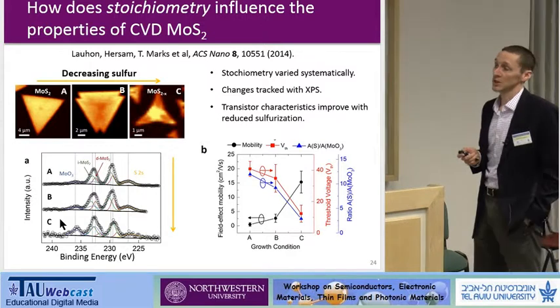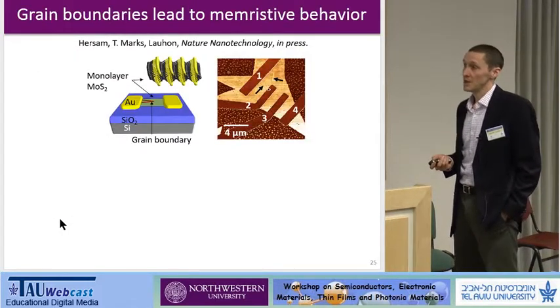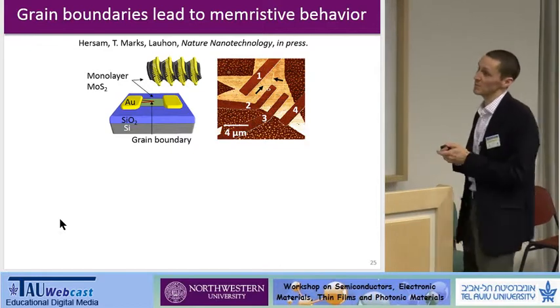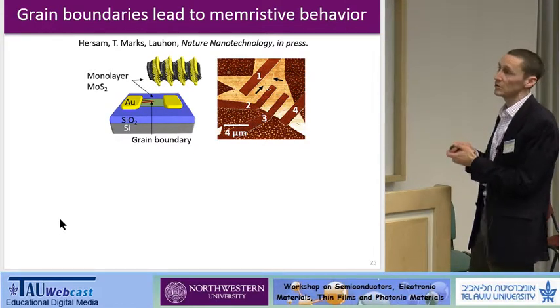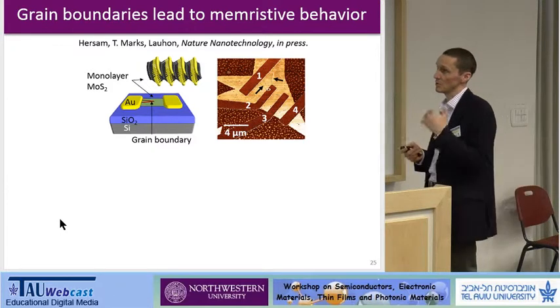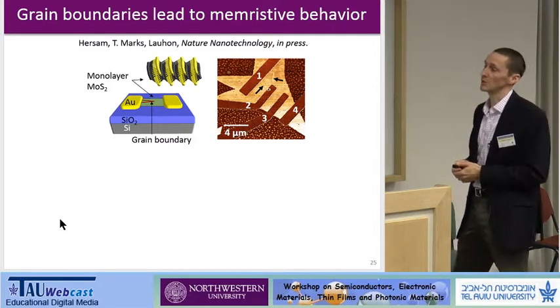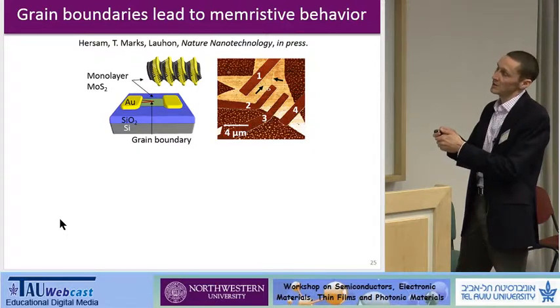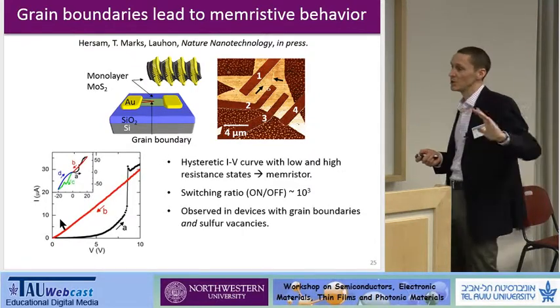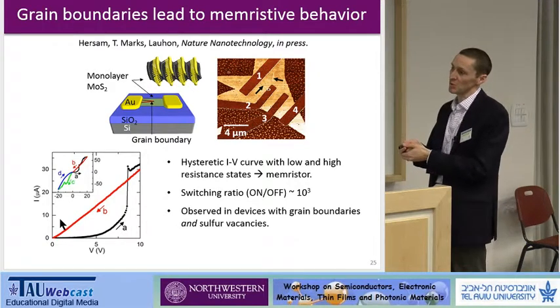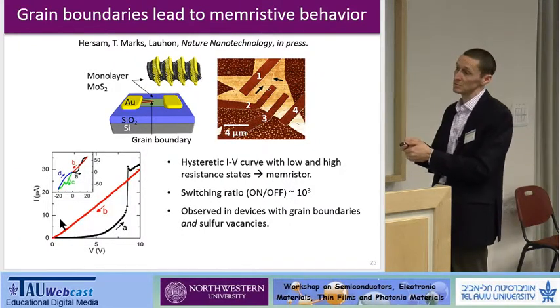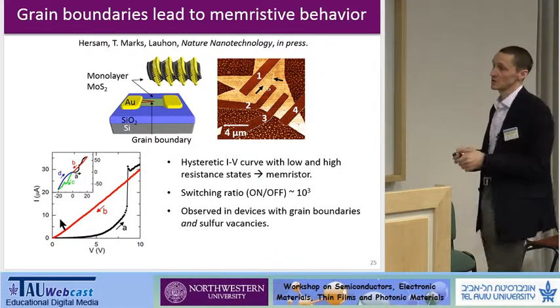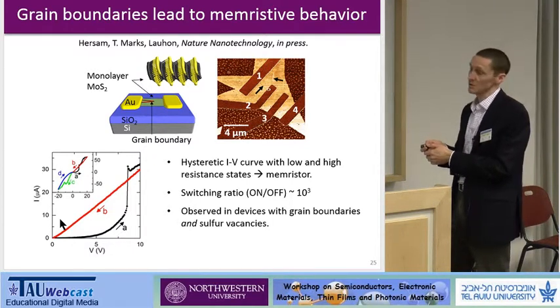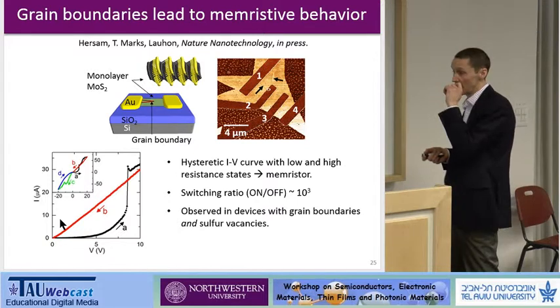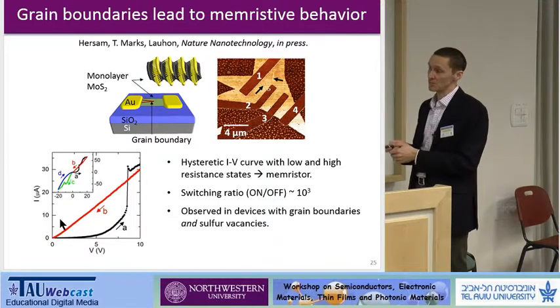But what's more interesting about these particular defective materials is that when they're sulfur deficient and they have grain boundaries at a particular geometry in the channel, they show memristive behavior. I think Mark will probably talk a little bit about this as well, and I won't go into it in detail. But in devices where there's a grain boundary within the channel, you can manipulate that grain boundary and see essentially a memory effect. There's a certain bias at which the device turns on to a higher conductance, and it will stay there upon decreasing the voltage. Okay, so this is the foundation for what is called memristive behavior with reasonable on-off ratios. And it occurs in devices, as I mentioned, with grain boundaries and sulfur vacancies.